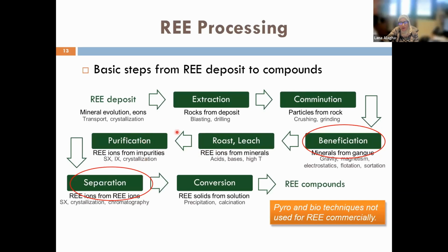And then after that, of course, solid-liquid separation followed by solution purification, where you can separate the rare earth salts from other salts that are in the leachate solution. This is done by different techniques, including ion exchange, crystallization, and solvent extraction. I'll focus more on solvent extraction.